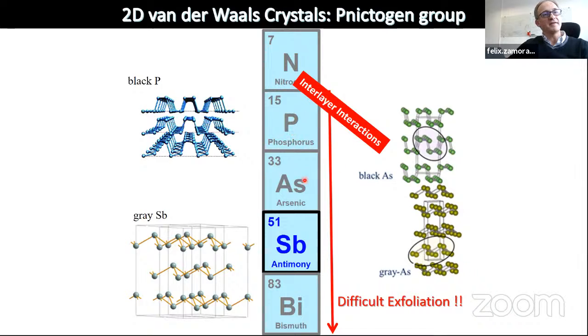But it's not the only element in this group. If we move down in the group, we find arsenic. Arsenic shows two allotropes of interest for us: the one isostructural with black phosphorus, which is black arsenic, showing the same structure, and another one called gray arsenic, showing this layered structure with a slightly different disposition of the atoms in the layer. This is isostructural with the one we have for antimony, gray antimony or beta antimony. So along the group we have different possibilities to start with materials and then delaminate them and try to form 2D materials.